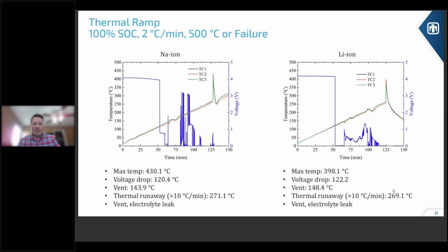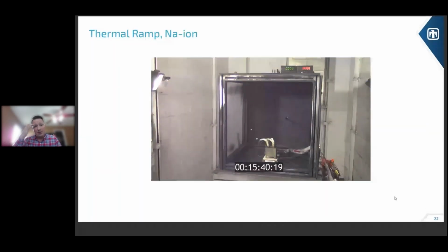We were a little perplexed by this at first. We actually did a repeat test just to make sure that this was valid, but it is, and if you think about it a little bit more, it makes some sense. Both of these sodium ion and lithium ion cells are layered metal oxide cathodes. They both have a carbon-containing anode, and they both have organic liquid electrolytes. So there's a very similar corollary and composition between both 18650 cells. Next. And I think there's another video of the thermal ramp.